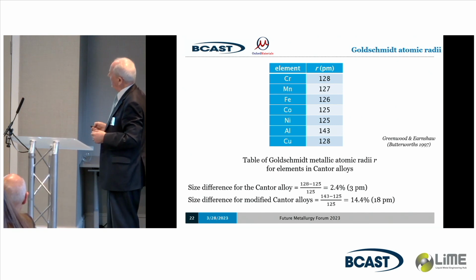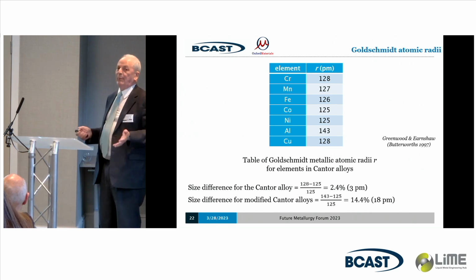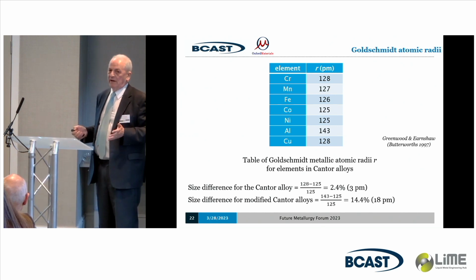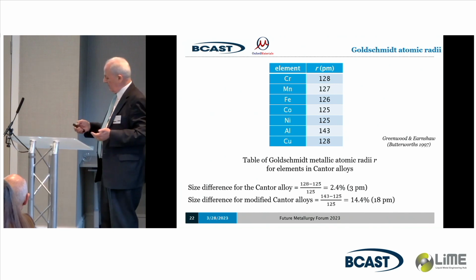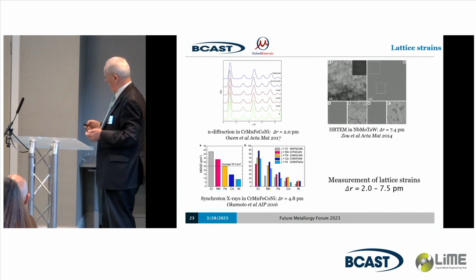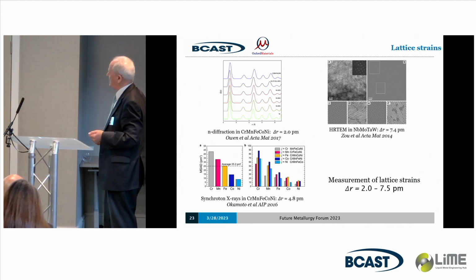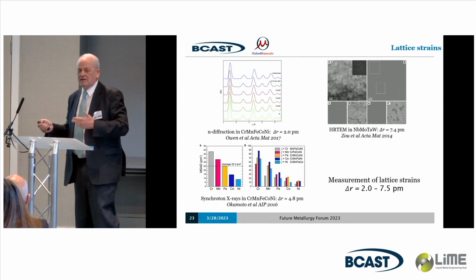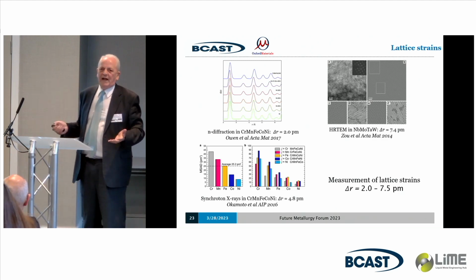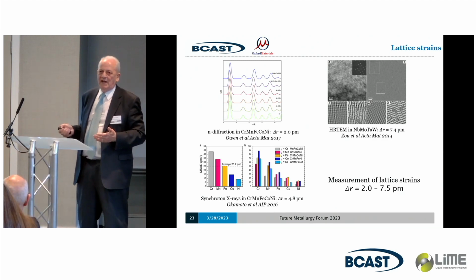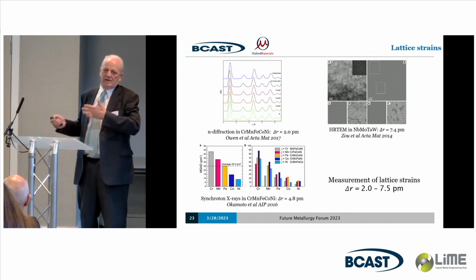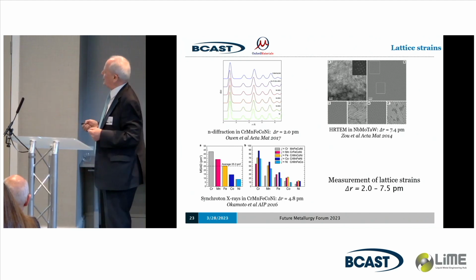So here's the Cantor alloy, 5 components. They differ by about 2.5%. That's a big strain at maximum, you'd expect. And it turns out that if you do neutron diffraction or synchrotron X-ray diffraction, that gives 2 picometers. This gives 5 picometers. So that's the right range. It was 3 picometers that was the prediction from the Goldschmidt radii, which is not a perfect prediction.